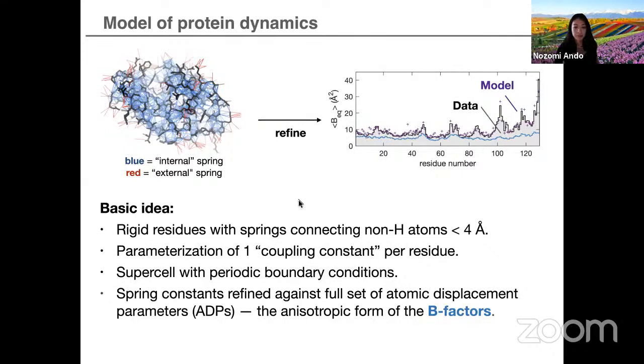And we were able to do that in part because we had such high resolution data that we had the full form of the B factors, the so-called atomic displacement parameters. So a lot of data per parameter. And what I'm showing here is the result of the refinement. Blue, again, is just the lattice dynamics, and black is the B factors from crystallographic refinement. And the purple crosses are the B factors from the model after refinement. So we get pretty reasonable agreement between the model and data.